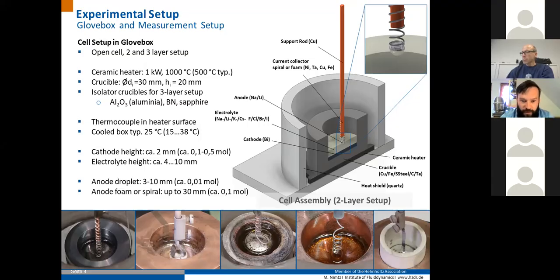We also had some, as you can see here, crucibles from copper or iron, which have shown some side reactions with the bismuth, for example. To have a very low reaction rate with the crucible material, tantalum or molybdenum or something like this is preferred. The diameter of the crucible usually is around 30 millimeters. We have some larger crucibles, but as I said, the cost goes up quite fast, and the knowledge you could gain by having larger cells is not that much higher. So we stick to the small cells.